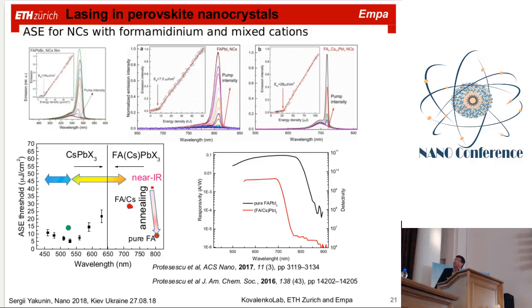So we also worked with surface chemistry in order to find very short ligands for these nanocrystals, in order to make intrinsically compact films already, without any additional washing or other kind of ligand exchange. So we found very nice ligands, which show pretty good properties, providing even lower threshold for optical gain. And those ligands were also very good for electrical transport in these layers. And they were also beneficial for making LEDs.